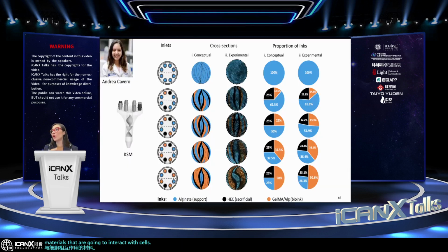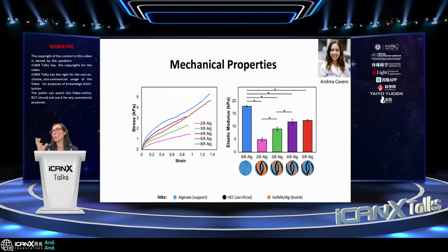So with this more degrees of freedom, what Andrea did was to explore different configurations and ratios of the bio ink, the sacrificial ink, and the support ink, to see what could be a sweet spot between reinforcing the fibers and maximizing the volume of the cells that we are going to print in our filaments. So what she found out is that these 2 configurations could be good candidates for incorporating cells.